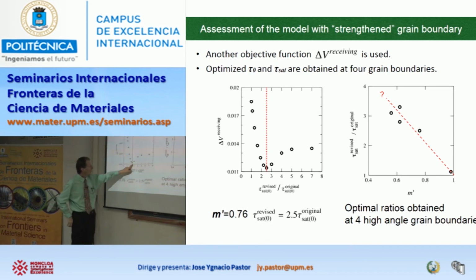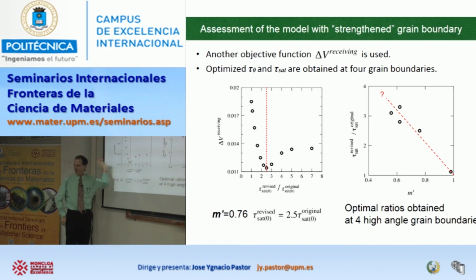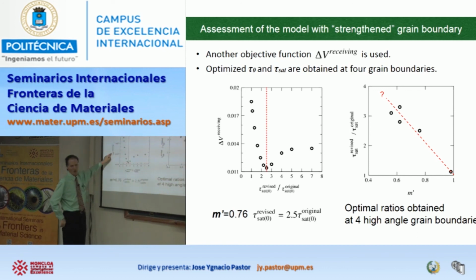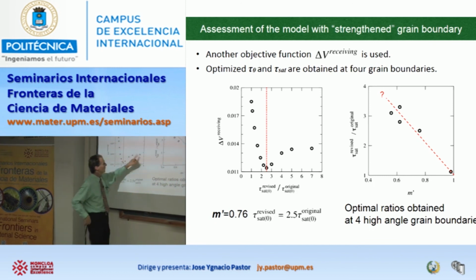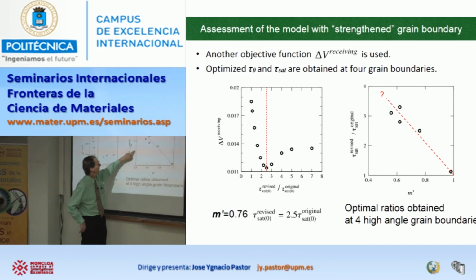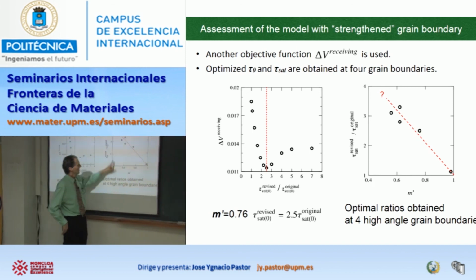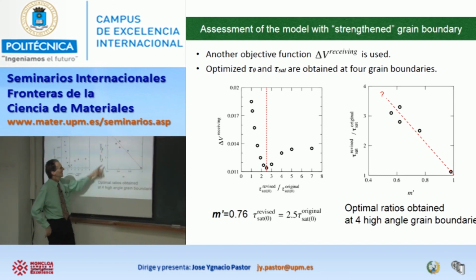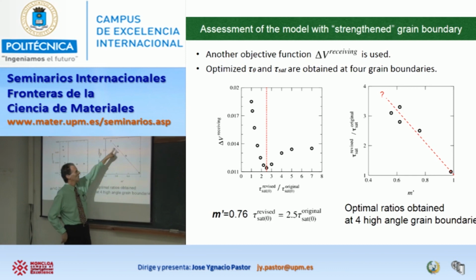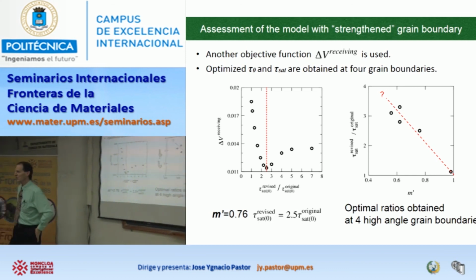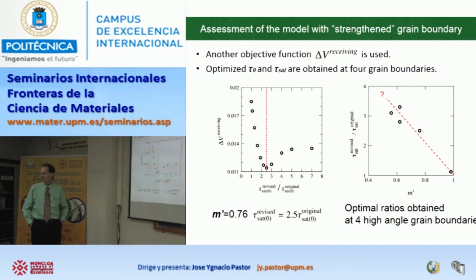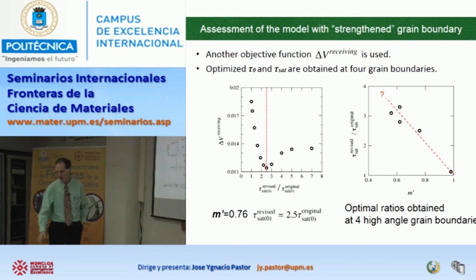So if I increase the hardness to, say, 2.5 times just in that thin layer, I can make that volume difference minimized. That means I know how much harder that layer needs to be for me to simulate what that indentation is doing. And that's kind of nice. So then if I plot these values, how much harder is it, 2.5, 3 times harder, with this M prime parameter, then maybe there's a trend here. But there's not enough data points there yet to be sure. But it suggests that there might be a relationship that we could actually build into a model.